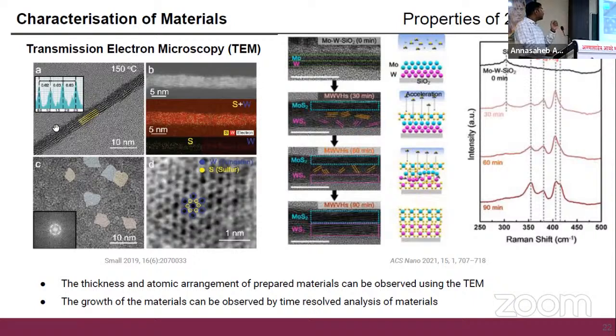Typically, the cross-sectional region is obtained by cutting the sample using an electron beam technique, which we call the focus ion beam technique. We cut the sample, and then in the TEM microscope we can see that region. This is the TEM image for WS2 synthesis reported by our group, where you can see 5 to 6 layer formation of these WS2 layers.